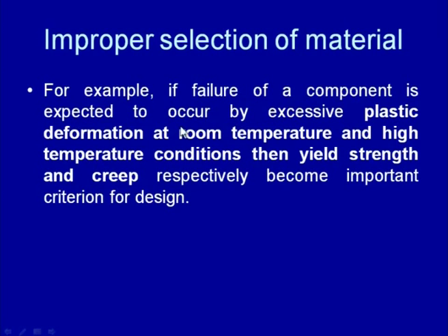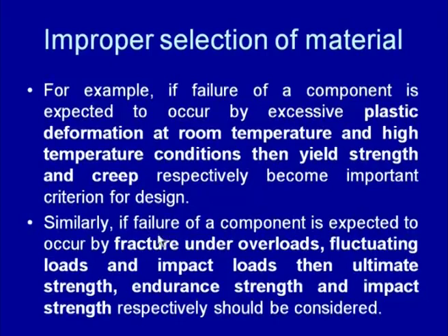For example, if the failure of the component is expected to occur by excessive plastic deformation at room temperature, then yield strength should be used as a criteria, and if it is expected that failure will occur at high temperature due to deformation at high temperature, then creep resistance should be used as a criteria for selection of the material. Similarly, if the failure of the component is expected to occur by fracture under overload, or fracture under fluctuating loads, or fracture under impact loads, then the ultimate strength, endurance strength and the impact strength respectively should be considered for selecting the suitable kind of material.